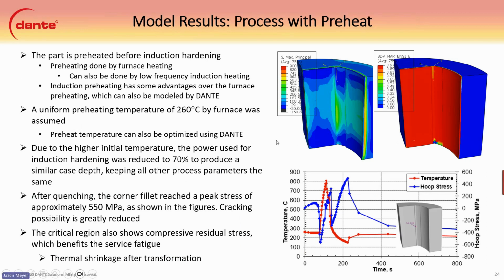So the last model they requested was the process with a preheat. This part was preheated before induction hardening, and it was modeled to be done by furnace heating, so taking it out of the furnace and then induction hardening afterwards. This also can be done with low frequency induction heating. The induction preheating has some advantages over the furnace preheating, and all of these can be modeled here with DANTE, mainly just the speed that they can do, hit it with a low power, low frequency, and then do the actual hardening process afterwards.